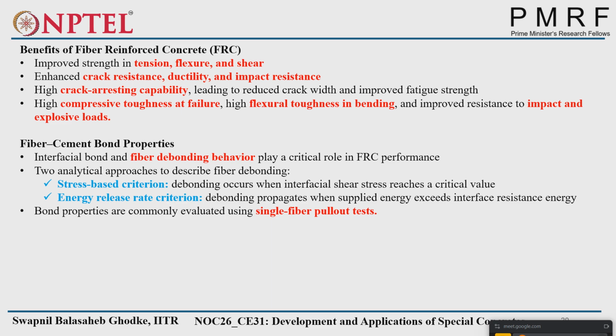But in the case of fibers, you need equipment which has the least count. In our institute, a 25 kilonewton UTM is used for the fiber pull-out test, because higher range equipment you cannot use. Similarly, we are using it for the rebar. With the help of this 25 kilonewton UTM, you will do the single fiber pull-out test, and based on that you will see the strength stress based criteria or energy release rate criteria.